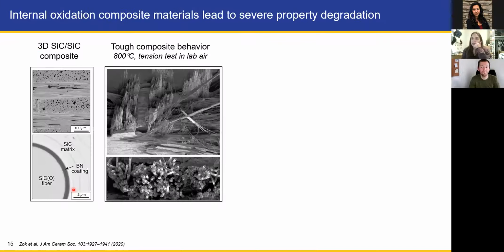So we can test these not only in those smaller components, but larger ones with lots more fibers. So this tough composite behavior you see with lots of fibers in this vertical direction, but also the horizontal direction where fibers are splaying everywhere. Again, this is the tough composite behavior that we want to see. This sample was tested in a tension test at 800 degrees C, just in the lab air.